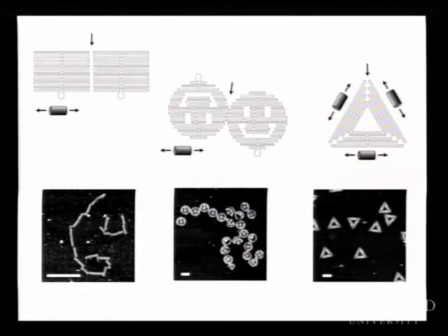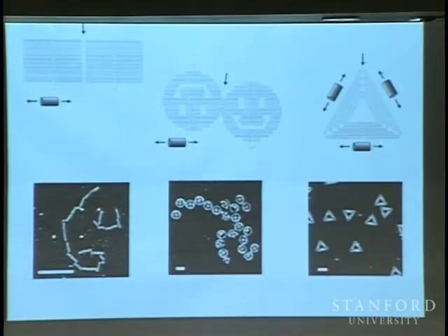And the difference is, if you look at the way that, so DNA is a double helix, but you can also at the nanoscale think of it as a rather stiff cylinder. In these rectangles, the cylinders all run parallel like this. And in the smiley faces, the cylinders all run parallel like this. But in the triangle, the cylinders are running in 3 different directions, and none of their ends are actually exposed. So all the ends of the DNA helices are hidden in this triangle, right? So the ends are what are sticking to each other, all right? So the flush cut ends of the cylinder, which don't have these A's, T's, C's, and G's. So normally the 2 strands come together, the A's meet the T's and the C's match the G's, okay.